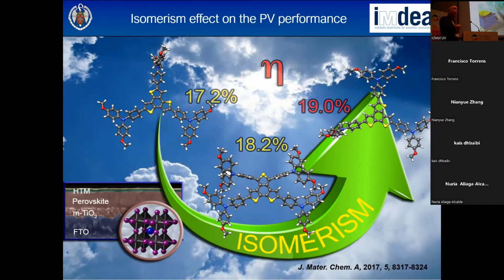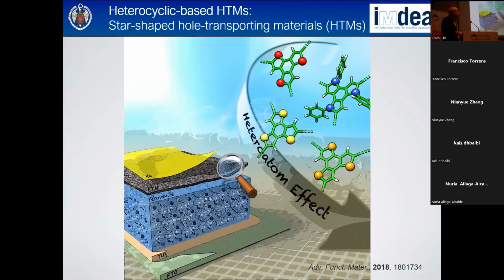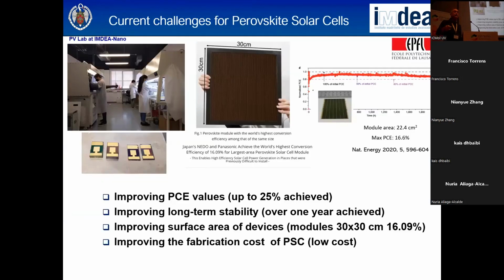Another thing, of course, you should understand: all these molecules were fully characterized and applied in the devices. Also, we played with the modification of the heteroatom. This was with the sulfur, but we also used oxygen, nitrogen, and selenium. And in these cases, interesting results surpassing 18% were reported for most of them.